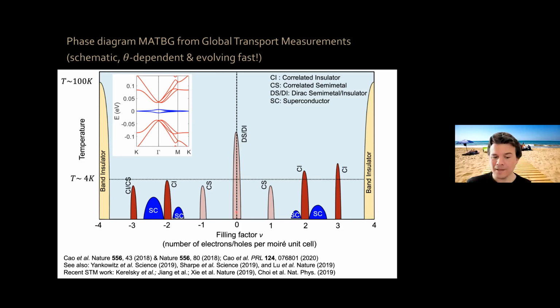Now, as we dope away from these correlated insulator states, you have superconducting domes. The most prominent is this one, when you dope extra holes around the correlated insulator state at 2 holes per moiré unit cell. But sometimes you also have this one, this one, this one, and occasionally there are a few others. So this is the phase diagram from transport measurements.